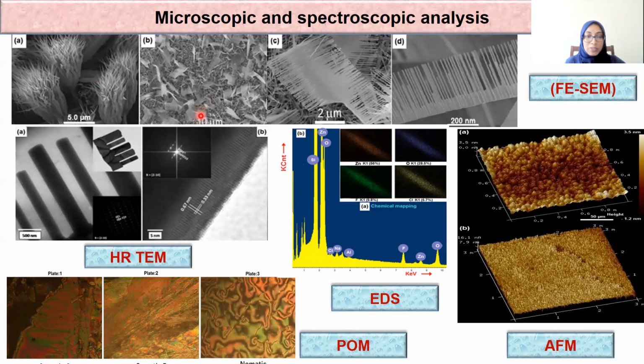And this figure, that is the figure B, shows the formation of self-organized single crystalline zinc oxide nanocomb. And this shows that the nanocombs are evenly spread and grown abundantly over the broad surface of the substrate. And this shows that the nanocomb consists of nano rod-like branches along the long ribbon-like stem.